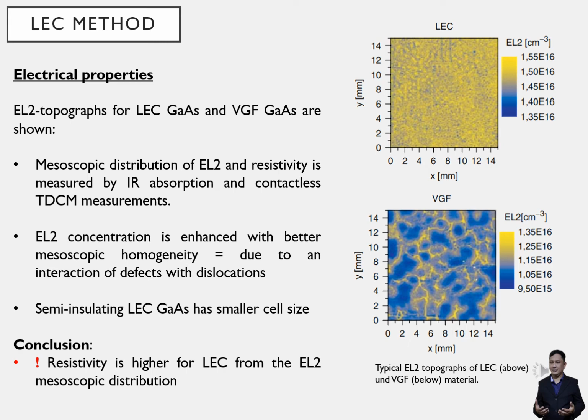For the electrical properties, typical EL2 topographs for LEC and VGF GaAs are shown here. Mesoscopic distribution of EL2 and resistivity is usually measured by IR absorption measurements and the contactless TDCM method. EL2 concentration is enhanced with better mesoscopic homogeneity and is due to an interaction of defects with dislocations, as can be seen in the LEC topographs. The larger cell size of VGF GaAs is clearly visible. With smaller cell size, the average EL2 concentration is higher in semi-insulating LEC grown GaAs compared to VGF grown GaAs. As can be concluded from the mesoscopic EL2 distribution, the mesoscopic homogeneity of the resistivity is higher for LEC compared to VGF material.